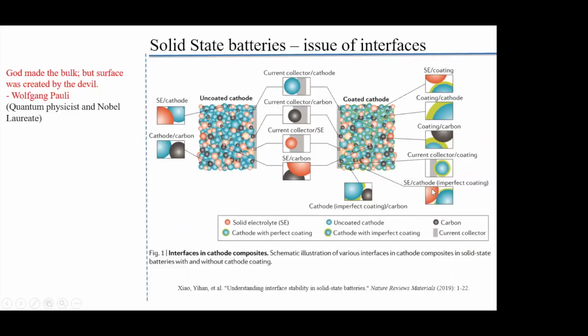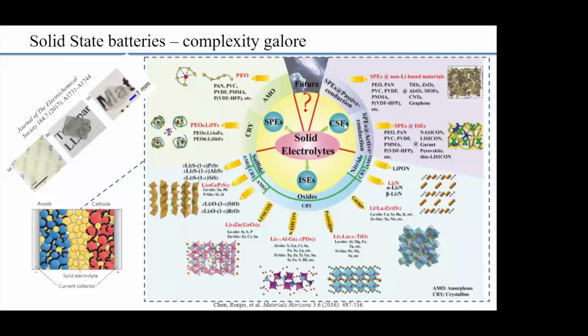But basically, you can coat some of the cathode materials and then mix it with the solid electrolyte particles. And you still need to ensure the contact is good, because if the contact is not good, it leads to a hotspot. It's like a tiny hotspot that can grow and grow and then lead to catastrophic failure. So that's the problem. The interfaces are something they must solve.